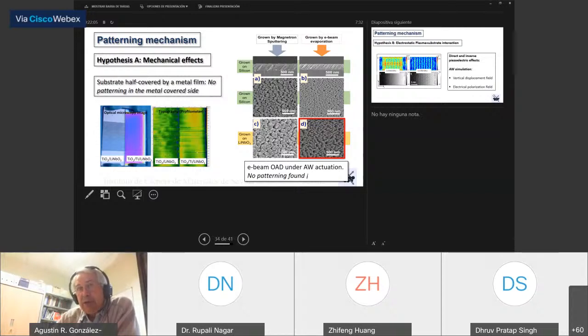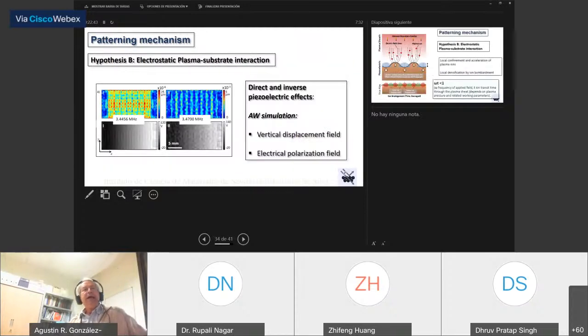Moreover, if we carry out a comparative analysis of the nanostructure obtained by electron beam oblique angle deposition excited by acoustic wave, what we obtain is the typical nanocolumnar deposition structure, you can see here, but without any patterning. So it means that something else, in addition to the mechanical activation, should be in place in order to produce the pattern. And the hypothesis that we are playing with is that in addition to mechanical actuation, we have the possibility of electrical actuation.